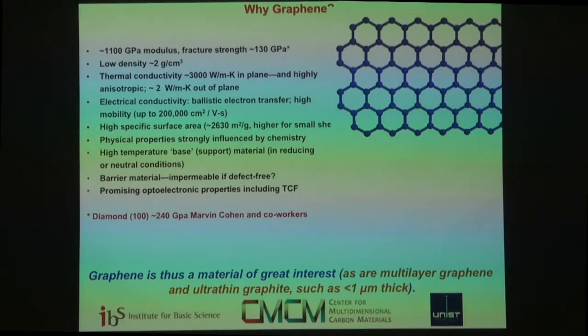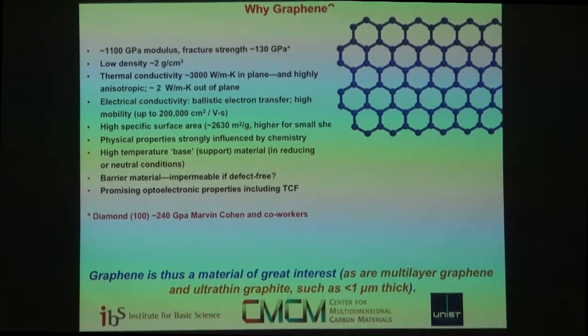Is glass a strong material? Remarkably, if you take the trouble, as some experimentalists have, to prepare fiber optic with very few surface flaws through careful polishing techniques, and then you make a measurement of the strength of glass at liquid helium or liquid nitrogen temperatures, so there's absolutely no water present, even though it has a modulus of only 80, silica, for example, it has a strength of 22 GPa. So you might ponder the implications of that in terms of my talk.